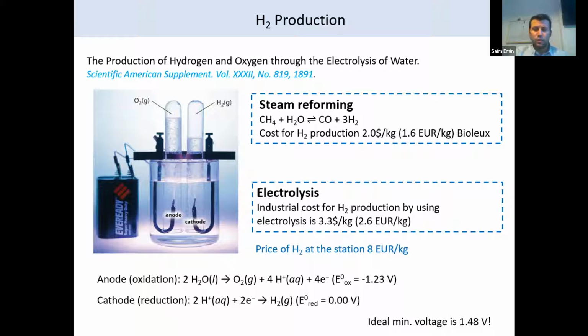Why is this 1.5 volts, or more specifically 1.48? Because we have losses. Usually in an acidic environment, water reduction is defined at 0 volts on the reversible hydrogen electrode scale, and water oxidation is at 1.23 volts. The difference is 1.23 volts between the reduction and oxidation. However, we have losses, and because of these losses, we need to apply a higher voltage.